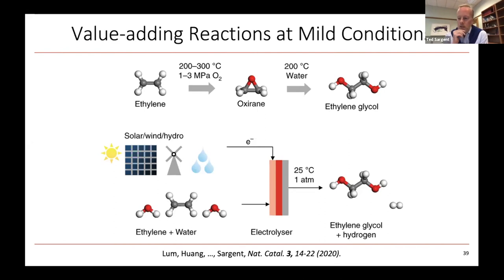So for example, ethylene glycol through the existing routes is a two-step process. It goes through the intermediate ethylene oxide, and it generates about 1.6 tons of CO2 per ton of ethylene glycol. And so we were very interested to explore whether we could develop a one-step electrochemical route.